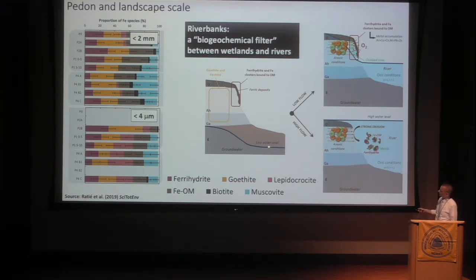What's unique about this system is that the buildup of the iron oxides and then the trace metals that are associated with them at these riverbanks could then be periodically flushed through weathering of these riverbanks. And so seasonally, we see that they observe changes in how the trace metals were built up here, and then a seasonal release of a pulse of colloids, of colloidal-bearing material, where these trace metals could be released.